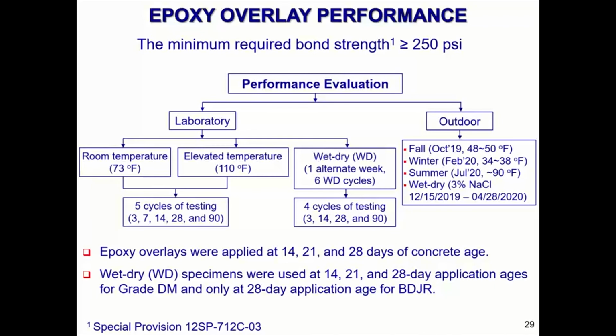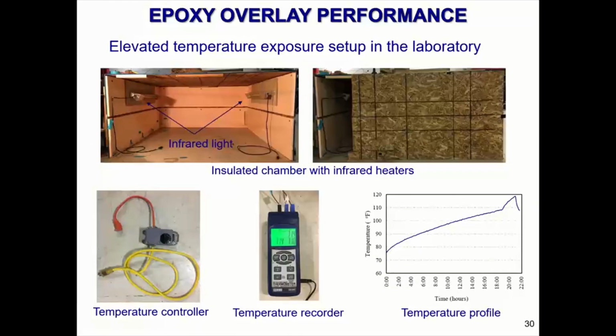When they did the testing, just to let you know, this is kind of a flow chart of how they looked at it. They tested our slabs that they made at room temperature, 73 degrees Fahrenheit. They tested our slabs at an elevated temperature of 110 degrees Fahrenheit, and they tested our slabs after alternating wet-dry cycles with a 3% salt solution flooded on the top of them. Here's some of the testing equipment in the lab that they used to heat up the slabs to 110 degrees.